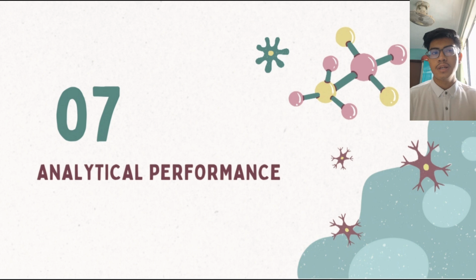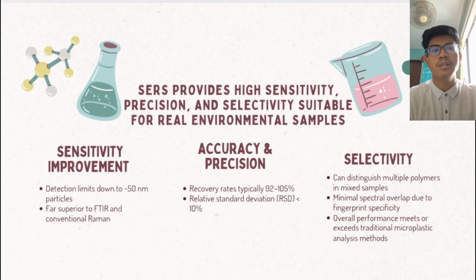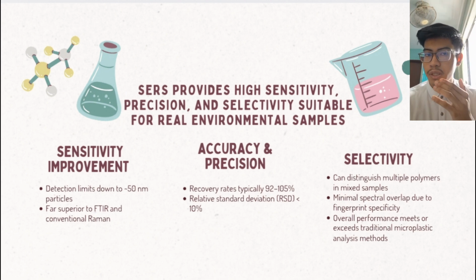In terms of analytical performance, SERS demonstrates excellent sensitivity, accuracy, precision, and selectivity. The sensitivity is particularly impressive, with a reported detection limit of approximately 50 nanometers, which is by far superior to conventional FTIR and standard Raman microscopy. Regarding accuracy, recovery values typically range between 92 and 105%, which indicates minimal systematic error. With high precision, relative standard deviation is generally below 10%, demonstrating good repeatability. In addition, SERS exhibits strong selectivity as it can distinguish multiple polymer types in mixed samples due to the unique fingerprint nature of Raman spectra.